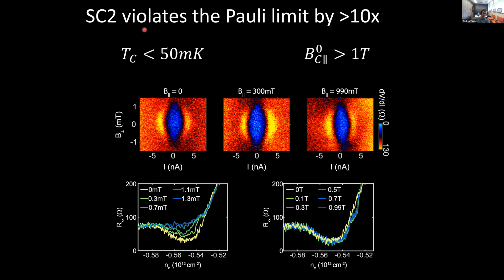So the transition temperature is less than 50 millikelvin, but you can essentially apply as large an in-plane field as permitted by our magnet and see no change, for example, in the out-of-plane critical field or the transition temperature. So even as 1 millitesla of out-of-plane field will destroy the superconductor, 1 Tesla of in-plane field has no discernible effect on it of any kind.